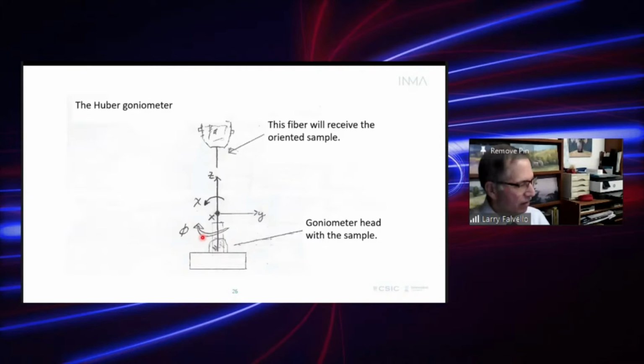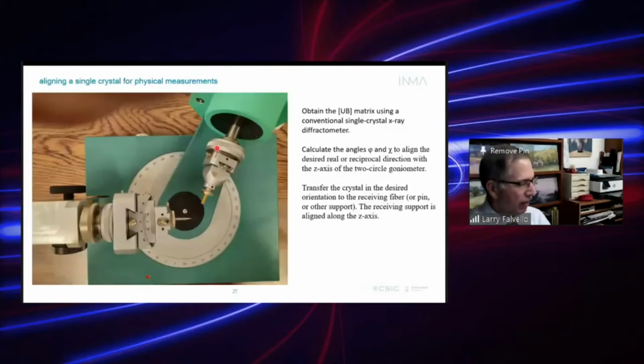Transfer that, still on the goniometer head, to the optical goniometer. You can simply calculate the 2 rotation angles you need to set in order to align the crystal, or any direction in the crystal, real or reciprocal, with the receiving support, which is along the z-axis of the optical goniometer. All right? So there's no sample in this photo. So you take your crystal from the diffractometer, put it right on up here, on the optical goniometer, set the angles so that the axis you want aligned is there, and mate the two supports.